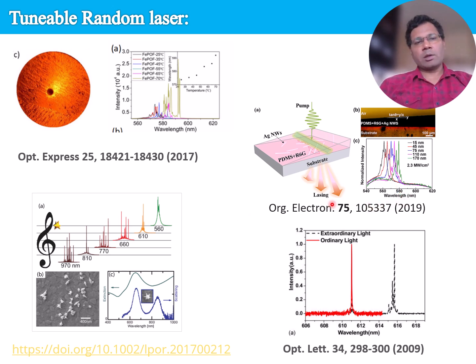Additionally, a wedge-shaped random laser composed of disordered silver nanoparticles embedded in a dye-doped polymer has been fabricated via press coating. Coherent feedback is enabled by both multiple scattering and plasmonic enhancement from the nanoparticles. By adjusting the excitation position along the thickness gradient of the wedge, the lasing wavelength can be tuned continuously from 560 to 580 nanometers due to the reabsorption effect. The thicker region of the wedge supports more lasing modes, enabling simultaneous multi-wavelength operation and mode selection, offering a simple yet very effective method for tuning random lasers.